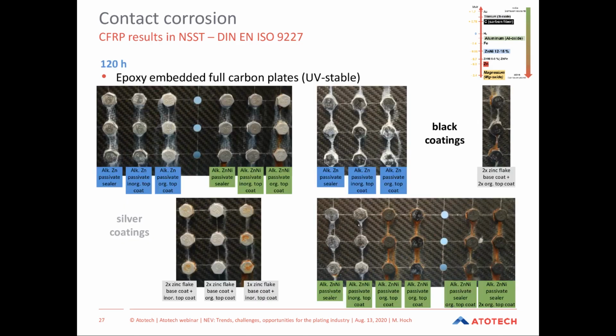Up to 120 hours, the results you see here. So we got in the neutral salt spray test acceptable results with zinc, zinc nickel, and some zinc flake systems with dedicated process selections. Not everything was good, but there are still some good systems, either in silver and in black coatings. But we also observed systems which already got severe corrosion, white corrosion as well as red corrosion, especially on the right bottom picture.